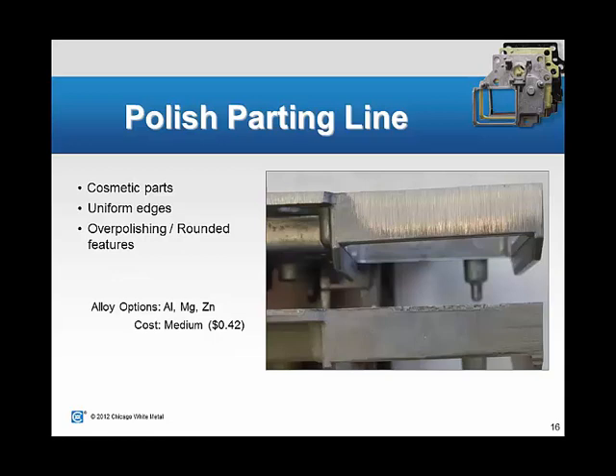For a lot of people, the as-trimmed look is fine. It's not a problem. If it's a highly cosmetic finish, many times that's not acceptable. Even if you powder coat or wet paint on top of this, the rough area will still show through. It's not like it'll cover up with powder coat or wet paint. It'll still show. So what we do is, again, a more manual process, we will actually polish the parting line, and the result of that is what's above.